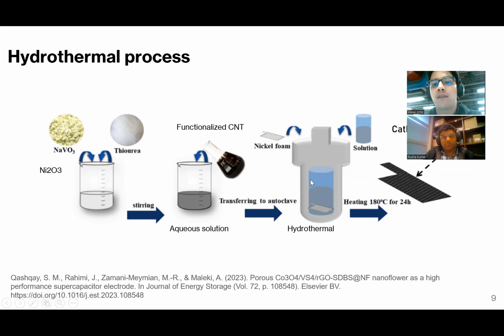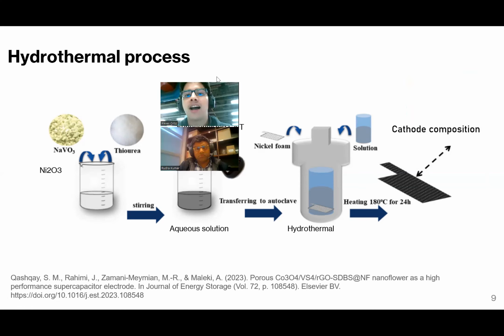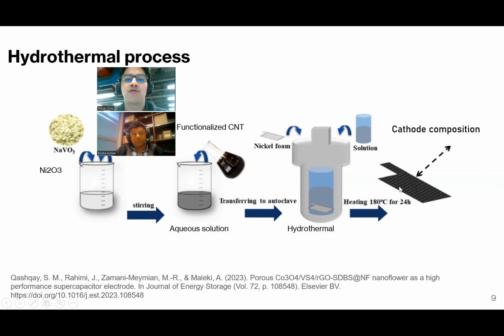Now, here is the part of the autoclave. That is where we put the nickel foam, which is the substrate, and also another source of nickel. Here we put the solution and the nickel, and we heat it to 180 degrees for 24 hours, for example, for our case. And finally, we put it in the oven to dry it, and we have the cathode composition.